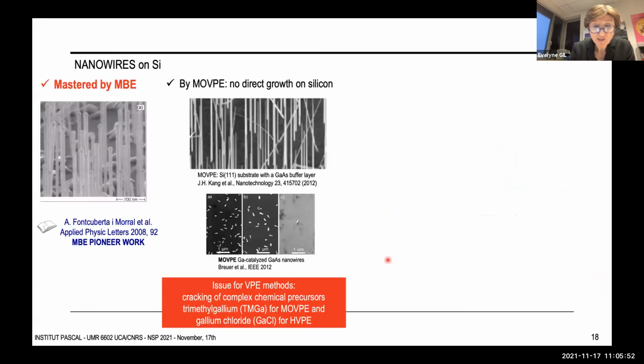One of the major interests of nanowires is the possibility to grow on silicon, as the lattice mismatch strain is relieved by elastic relaxation at the nanowire surfaces. And the goal is not only to reduce the global cost of devices, but also to achieve the successful monolithic integration of III-V photonic structures and functions with silicon circuits. So when it comes to that matter, MBE performs very well. And here with the pioneer work of Anna Fontcuberta i Morral and then all the consecutive successes.